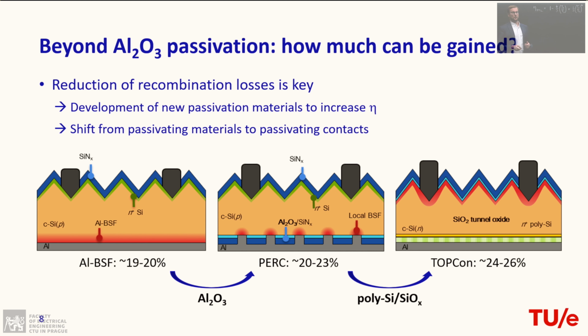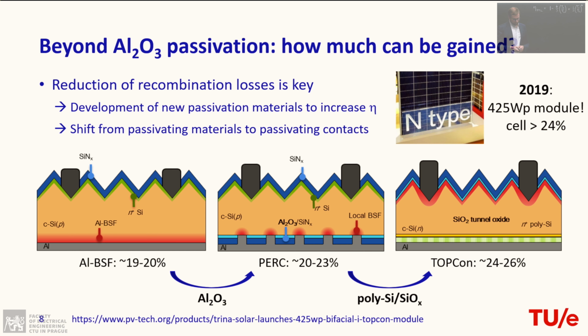You would like to have a full contact that is also passivating, and that is what you see on the right-hand side over here, which is nowadays known as the TOPCon structure. It was first pioneered by Fraunhofer in Germany, but the structure actually is not that new. They make use of technology already from the 1980s, which is a combination of doped polysilicon with a very thin silicon oxide layer in between. This silicon oxide is basically acting as a chemical passivation layer, and the doping in your polysilicon provides the field effect, in basic terms at least. So even if you do it like this, your efficiency can already exceed 25%, and there are even companies now in China already making these kinds of modules. I have one example shown over here.